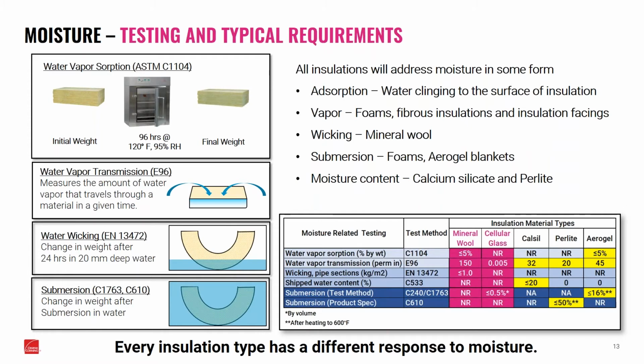Then we have something that's new to the market, which is water wicking, and you'll see this with mineral wool, and there are some other insulation types that have tested this as well. Essentially, this test is mimicking leaving the insulation outside, exposed to the elements. How much water is it going to wick into the material? We're just putting a section of material into a bath of water that's 20 millimeters deep, about 5/8 of an inch to 3/4 of an inch, and we're taking the weight before and after to determine how much water is wicked up into that material.